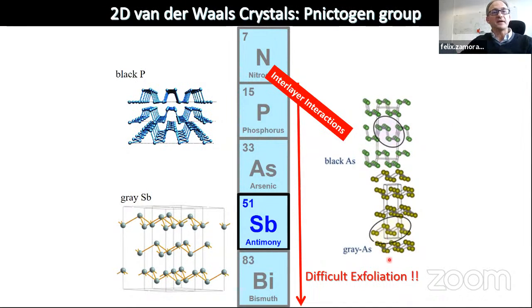The problem that I had at that time is that I couldn't find any student. I brought the arsenic, those are the crystals of arsenic, you can believe me. But I couldn't find students to work with this material. I don't know the reason why. So I moved further down in the group, and passed to antimony. We have the crystals of this material, and we started with this delamination. But you have to take into account that as you move down the group, the interlayer interaction between all these allotropes becomes stronger and stronger. Therefore, we envision problems with the exfoliation as you move from phosphorus to arsenic and so on.